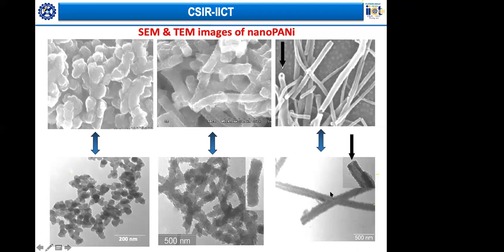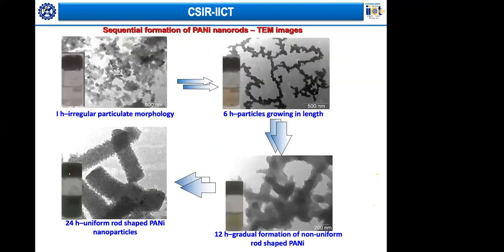So here we are trying to understand the shape versus selectivity for various applications. At various intervals of time, we try to look at the shapes. It's an irregular kind of thing at about 1 hour after starting the polymerization. By 6 hours, it shows some irregular shapes, and particle growth and self-assembling is taking place. By 12 hours, you start to see the formation of rods, but by 24 hours, you can very clearly see these are crystalline, and they are nicely decorated in the form of rods.